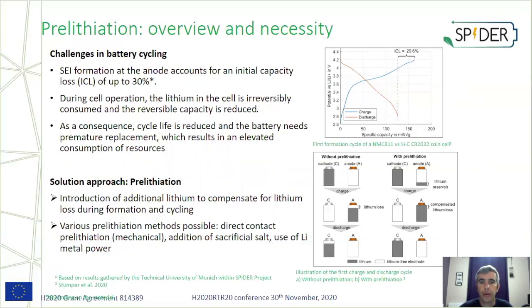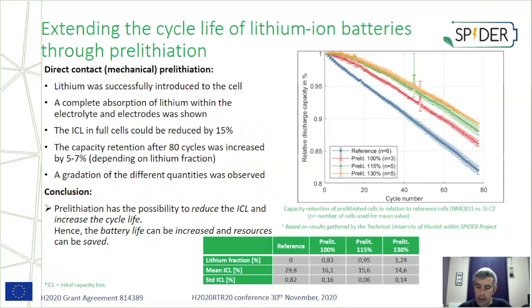A solution to reduce the lithium loss is to introduce additional lithium within the cell. And there are various prelithiation methods which are possible. In the project, we are working on the use of lithium metal for direct contact prelithiation, the synthesis and addition of sacrificial salts, and also the use of lithium metal powder. We demonstrated a successful introduction of lithium metal in the cell with a reduction of the initial capacity loss by 15%, and the capacity retention is increased. There is a gradation of the different quantities which was observed.